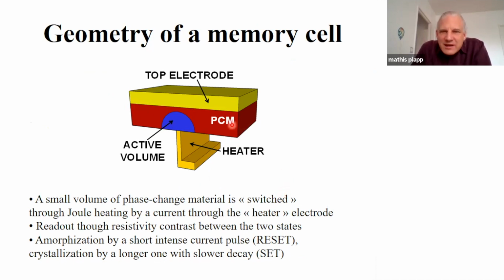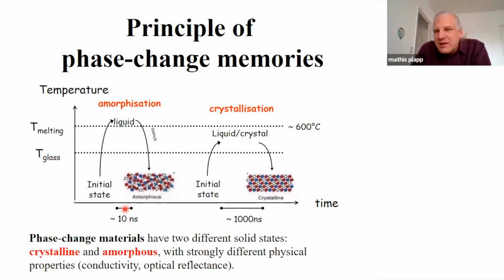Now, in the technology that, among others, ST Microelectronics is producing, a memory cell is 1 bit of this type. So you have a layer of this phase change material, enclosed between 2 electrodes. One is called the heater electrode and the other one is called the top electrode, because in these devices, the heating is actually produced by current. If you send current pulses through this heater electrode, through the Joule effect, it will produce heat. If you send a short and intense current pulse, it will lead to the formation of the amorphous state. And if you send a longer one with a trailing end, then you will crystallize. And that's how these time scales come. The pulse for making the material amorphous is typically very short, 10 nanoseconds. And the pulse that makes it crystalline is longer, from 100 to 1000 ns.